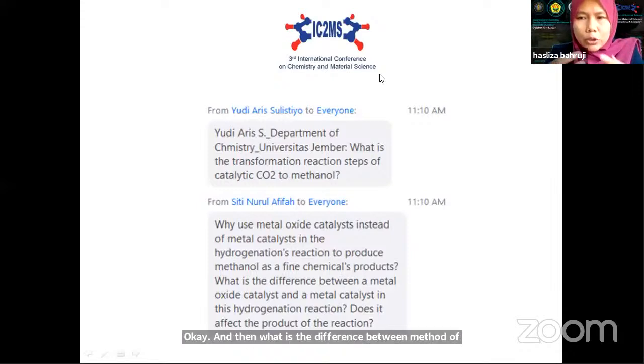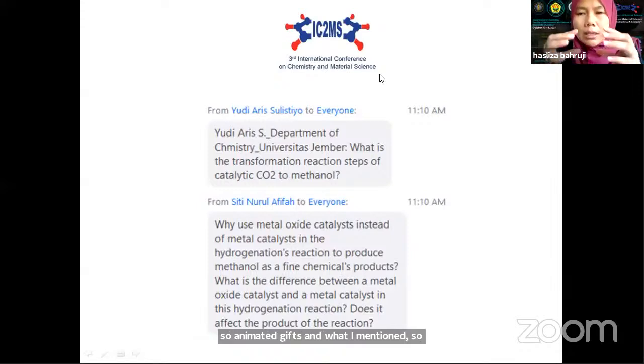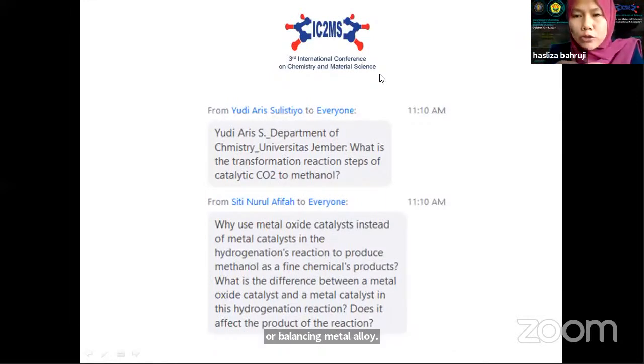This is what I mentioned. Metal is the site for hydrogen dissociation. Remember that we have carbon dioxide and hydrogen gas. Hydrogen gas needs to be dissociated into hydrogen atoms in order for reduction to occur. This dissociation of hydrogen occurs on palladium metal or palladium zinc metal alloy. But CO2 absorption occurs on your metal oxide.